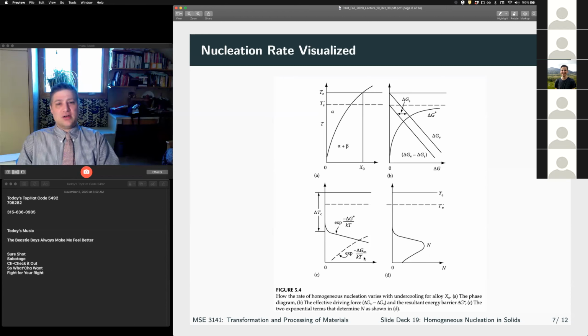And this is important because this is how we quench in a desired microstructure, right? So what we may do is, obviously, if I go from alpha down to room temperature, I no longer have mobility, right? So I'm going to stay at pure alpha.